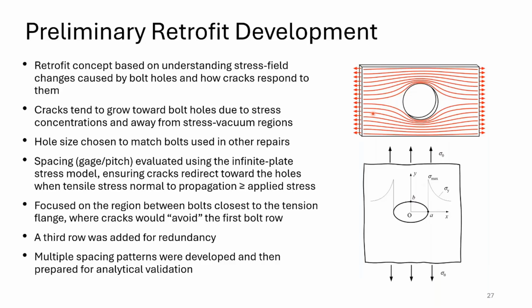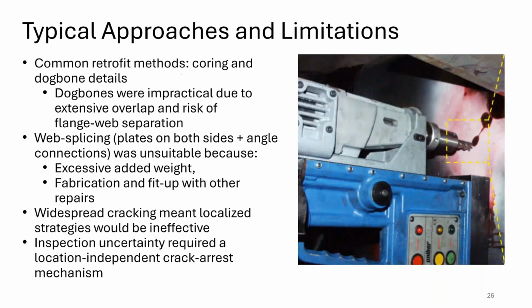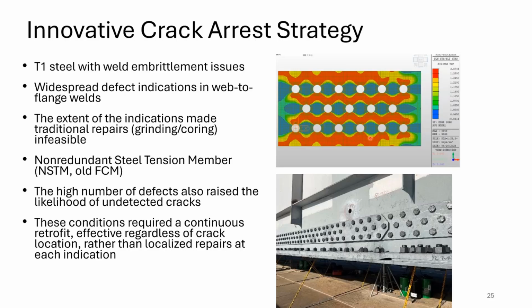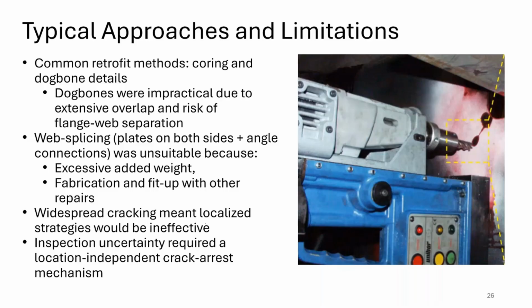To further emphasize this, look at this plot where we have a set of holes that are going to be used as the crack propagation repair. The red areas are locations in which the opening stresses have increased, and the blue areas are where we have that vacuum. The concept is that a crack originating anywhere along the web to flange location will either find its way to the hole, or if it misses this one, will find its way to the next one. So that's where the development comes from.